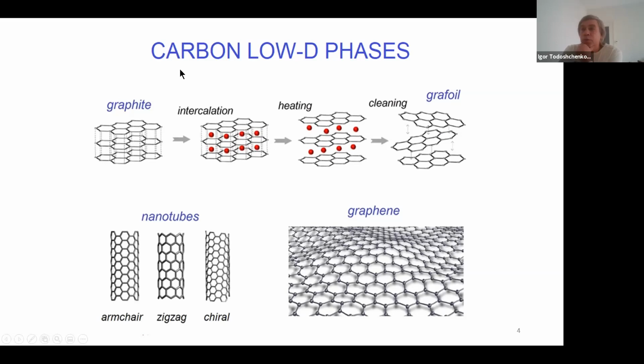What is a carbon nanotube? If you take usual graphite, it consists of very symmetric C6 planes, which are very weakly coupled one to another. There is very weak van der Waals coupling, which allows you to separate them by putting in gas, then heating, and these planes become detached. Finally, you clean, you pump out this gas, and you find some flakes of this C6 plane, more or less, so that this is grafoil or exfoliated graphite. If you take a single flake, this is graphene. If you now take a piece of this graphene, roll it up, and glue it, you form the nanotube.